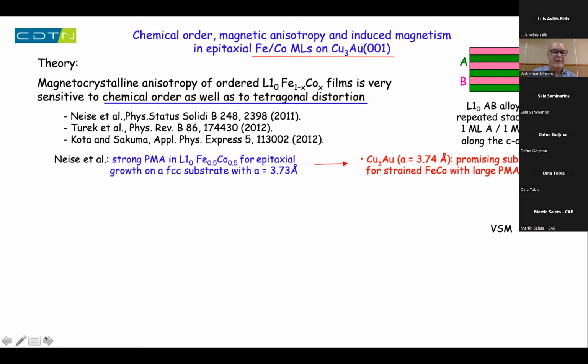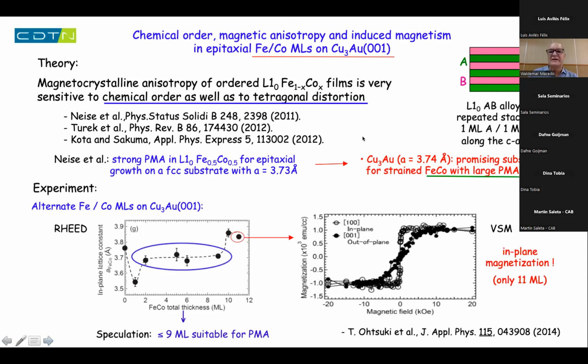Okay, and based on this calculation that the chemical order could also favor the perpendicular magnetic anisotropy in the system, these guys did the only experimental work that we know. They have grown alternate single monolayers of iron cobalt, that means to make an ordered stack of iron cobalt on top of copper 3 gold. But they did see in-plane magnetization for 11 monolayers. But they speculated that below 9 monolayers, we should observe perpendicular anisotropy.